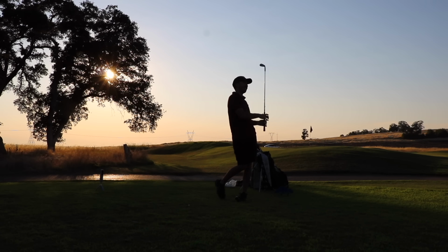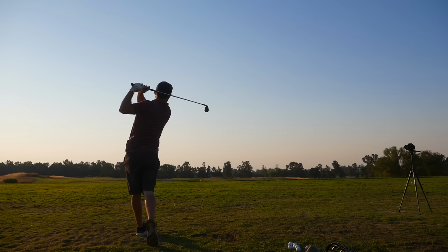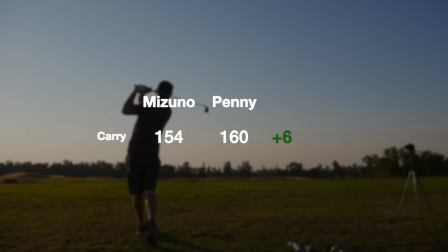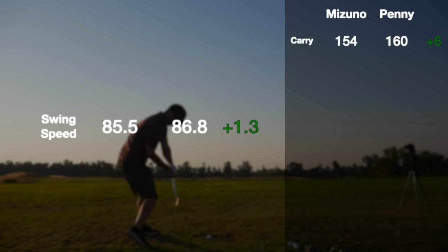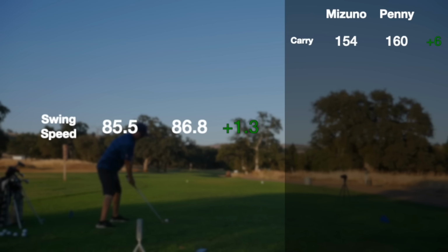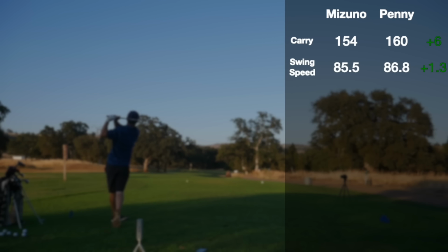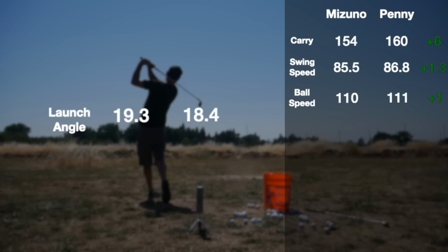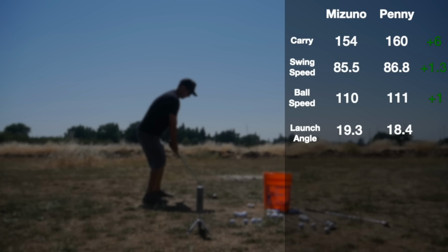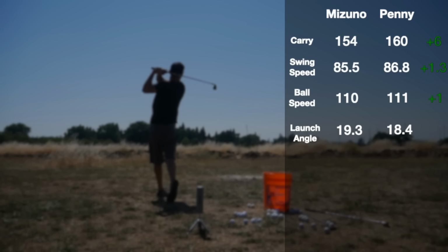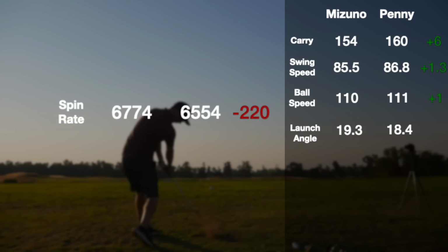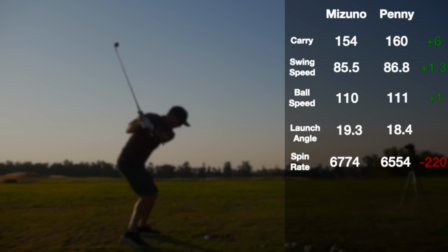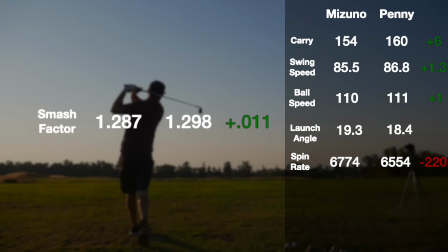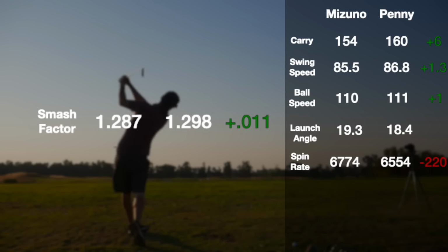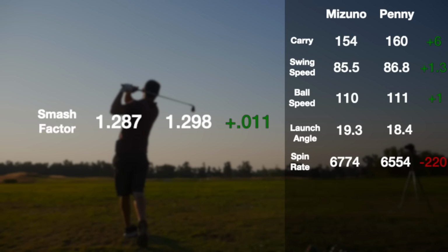These are Packard's stat comparisons for the Mizuno versus the penny iron. He ended up carrying the penny iron 6 yards further on average than the Mizuno. His swing speed was a tad bit faster using the penny iron, which makes sense considering it's a lighter club. Ball speed was 1 mile an hour faster. Launch angle was slightly lower on the penny iron, but still really close. The shot apex was also nearly identical between the two. Spin rate was down 220 RPMs, which could be due to a number of different factors. And his smash factor was overall better with the penny iron, which is a measurement of how well he transferred energy with the club. It's basically an efficiency measurement.